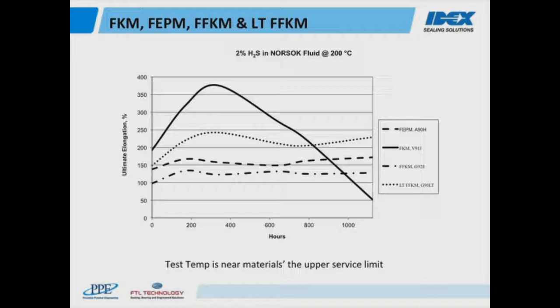What's immediately obvious is that the FKM, represented by the solid line, exhibited significant change throughout the test period. It has a rapid rise in elongation that is followed by a rapid decline. At the end of the test, the sample is brittle and no longer elastomeric. In a critical seal that is expected to last for many years, stability of properties is key. The other three materials tested have relatively stable ultimate elongations. We therefore observe that FEPM, FFKM, and low temperature FFKM are generally non-reactive in a sour environment.